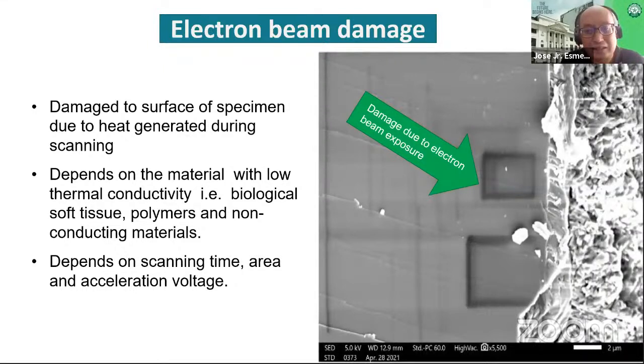And of course, as I said before, because of the high acceleration voltage and high energy electrons, you tend to create more damage on the surfaces. You can see this circular square and these things. These are the scan lines of the electrons. If you focus at a certain area at high electron volts, you can see these squares produced during focusing. So it depends on the scanning time. The longer I spend on the surface of the sample, the more damage you get on that element.